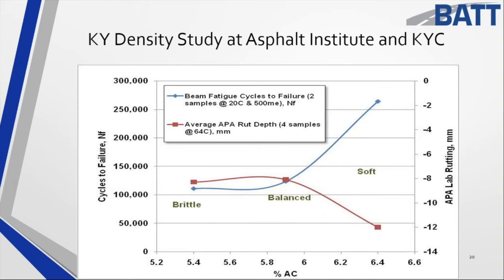In Kentucky, I struggle to keep dust out of the mixture because of my limestone that breaks down. Whereas in the southeast or northeast, with a very clean hard aggregate such as granite, I may struggle to get enough dust in my mixture. It's going to be different for everybody because we're talking about materials mined out of the ground and blended with a locally available asphalt that could be from a Canadian crude, Alaskan crude, southwest crude, or Gulf Coast crude. You start at the beginning — get a rut number, get a crack number, chart your way through, and make notes.